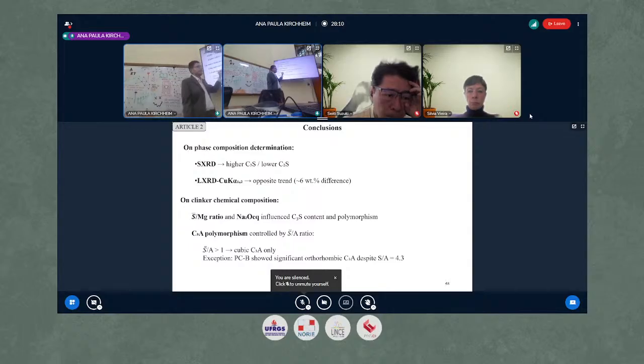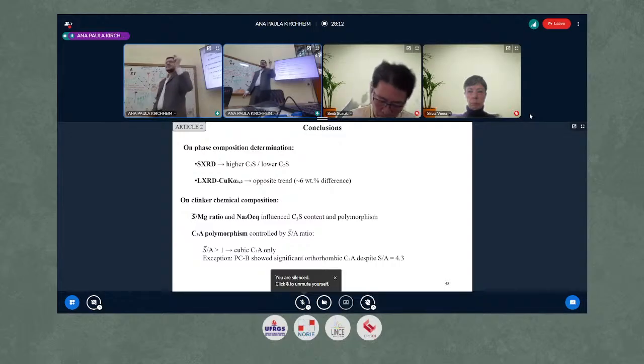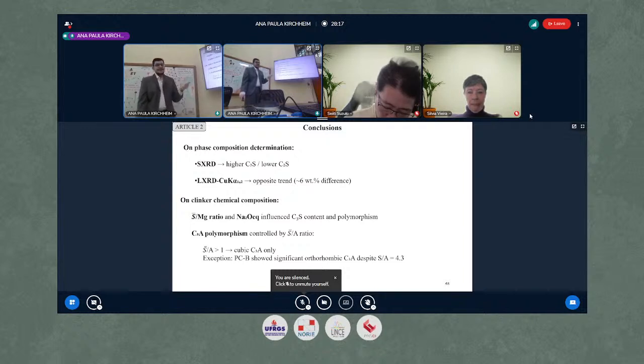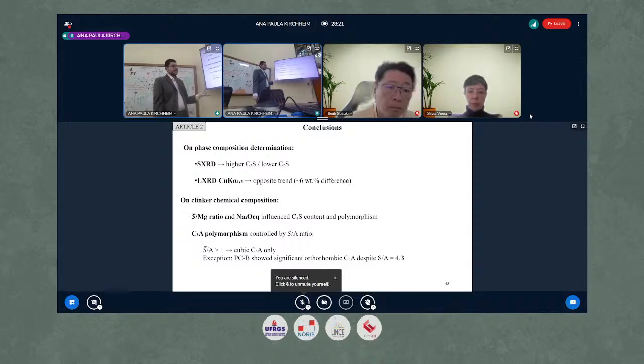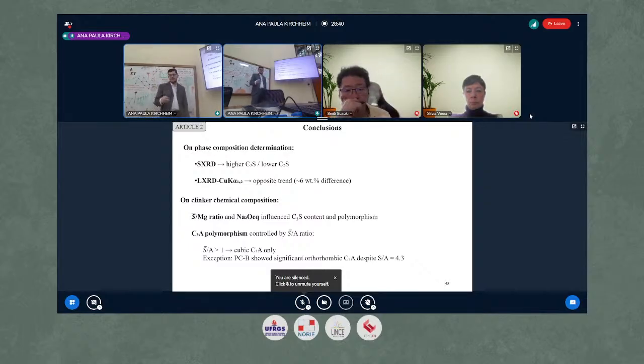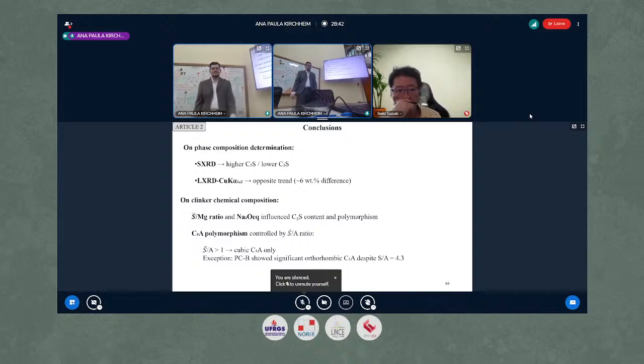and C3S polymorphism. Sulfate stabilized more belite instead of alite, but stabilized C3S M1, while magnesium and alkalis stabilized more C3S and more C3S M3. We also see again the great influence of the sulfate-alkali ratio on C3A polymorphism, but an exception was PCB, which also had orthorhombic despite having a sulfate-alkali ratio very much above 1.